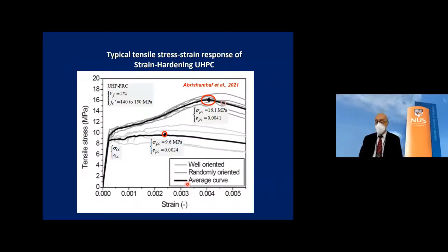Okay, this is an example of an actual UHPC stress-strain curve obtained from a recent study by Abrishambaf and a colleague. The reason this is here is I was interested at some point in studying the strain capacity of this material, but you could see it's just beautiful. In this case, the fibers have been oriented, so you get a beautiful stress-strain response, strain hardening, reasonable strain capacity at the maximum, and so on.